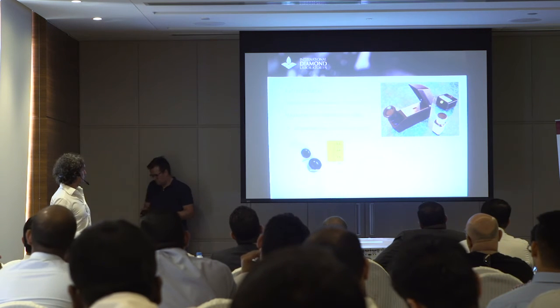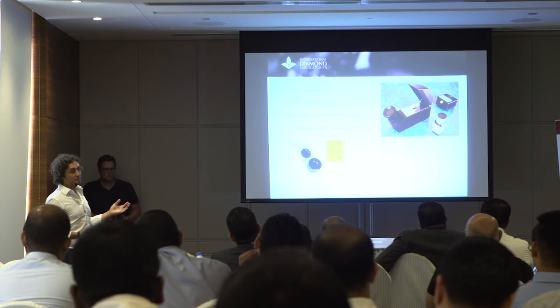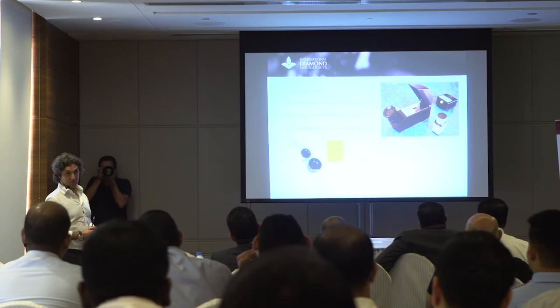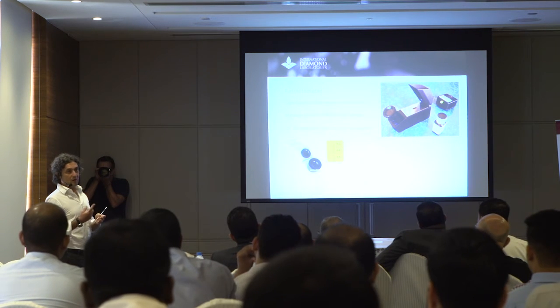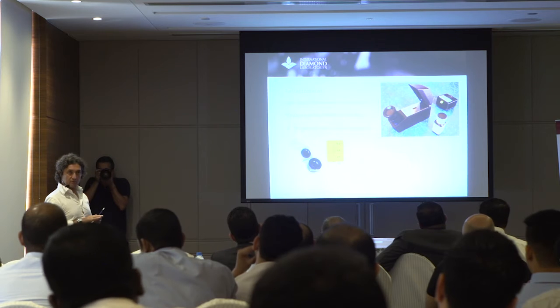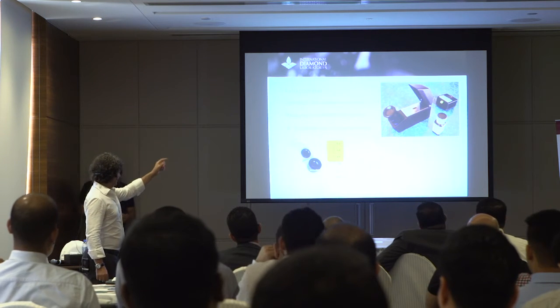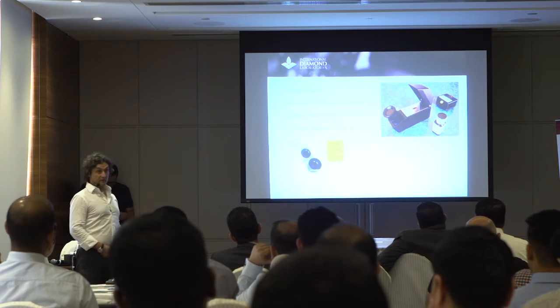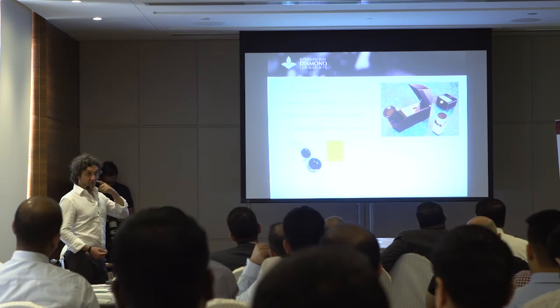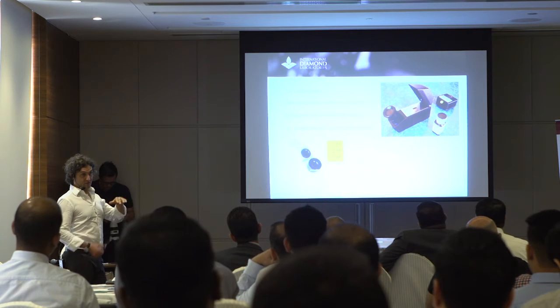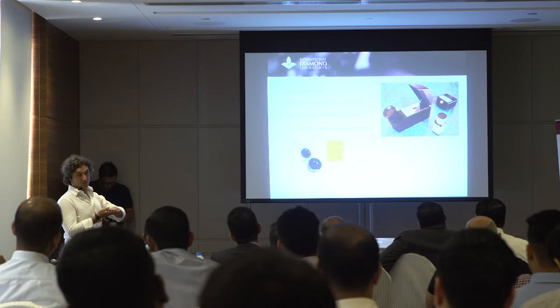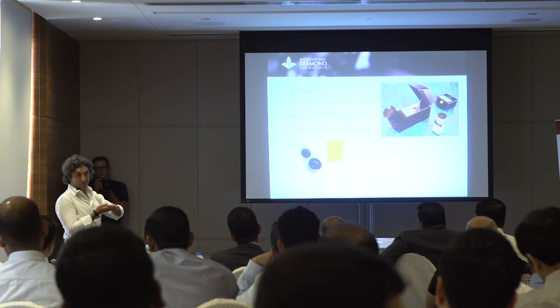The problem is this works only for faceted stones. So I need at least one polished facet. I need to place a little bit of contact liquid on the refractometer because I need to exclude air, otherwise I will measure the air.